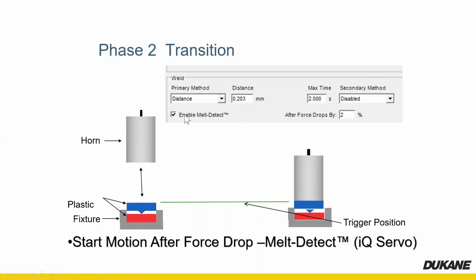So we've got, in this instance, our melt detect turned on, and with melt detect, we have an amount of force that we can look for to fall away. This percentage depends on the trigger force you're using and how big the parts are. There's a few different considerations we make when determining how much that percentage should be, but we usually have that all set for you when we're setting up your process. But it needs to be something. We've done a bunch of experiments and found that without any melt detect, the overall strength and the consistency of the parts is way more variable and way less strong than when we've got some melt detect enabled.